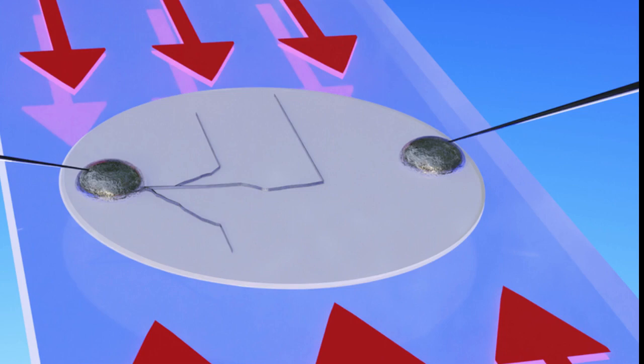The process of dendrite formation normally takes place deep within the opaque materials of the battery cell and cannot be observed directly. So the researchers developed a way of making thin cells using a transparent electrolyte, allowing the whole process to be directly seen and recorded. The team demonstrated that they could directly manipulate the growth of dendrites simply by applying and releasing pressure, causing the dendrites to zigzag in perfect alignment with the direction of the force.